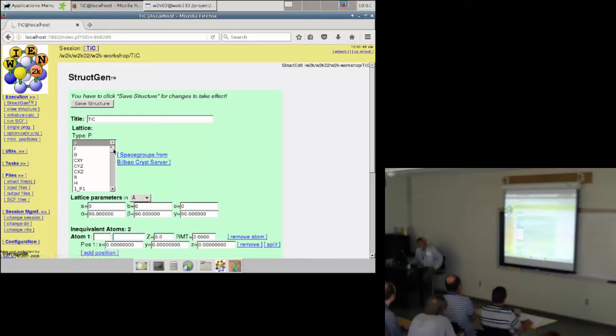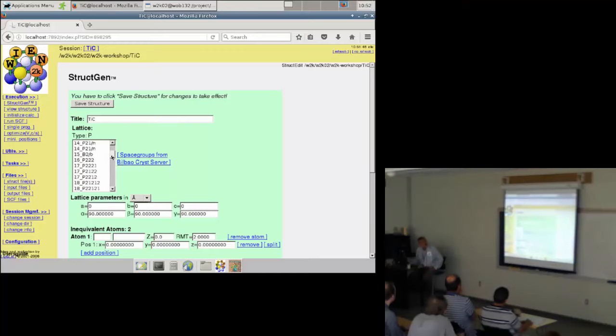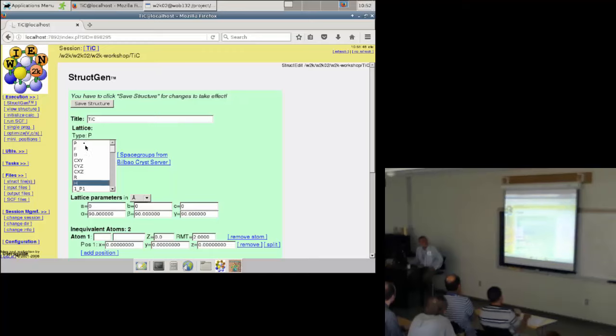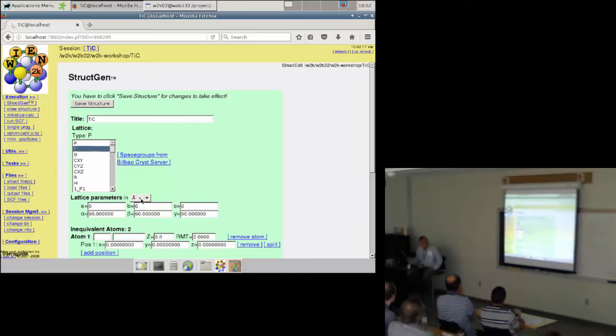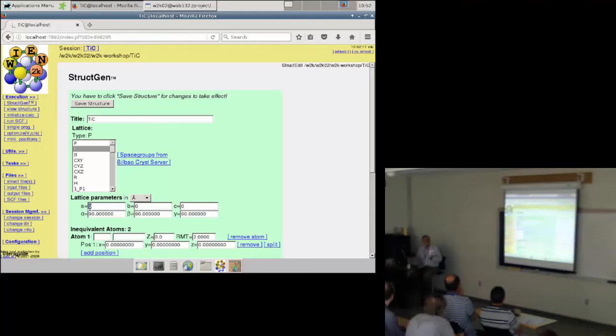It opens this template. You can put a title if you want. The first important thing to define a structure is to define the lattice. Wien2k offers two possibilities: either you tell it which lattice type you have — primitive, face-centered, body-centered, C-centered, rhombohedral, or hexagonal — or one of the 230 space groups. If you know which space group your compound has, select the proper space group. For titanium carbide I don't know it, but I know the sodium chloride structure is a face-centered structure, so I use 'F'. Then I put in the lattice parameters, which can be in angstrom or in bohr.